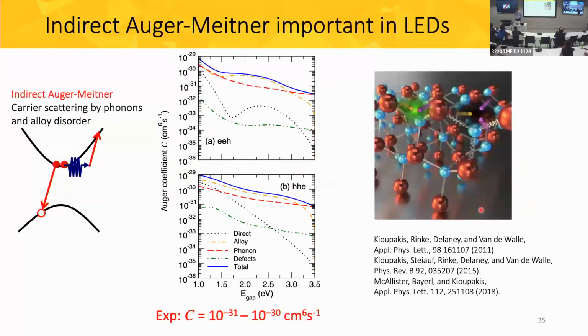A big part of that has to do with the Auger-Meitner effect: the carrier scattering by the phonons and by the alloy disorder gives rise to Auger-Meitner coefficients on the order of 10 to the minus 31, which agree with the range of experimental data, and that explains the potential origin of the efficiency reduction in LEDs. As we see in this cartoon picture, what we want is for an electron and a hole to recombine and give us light, but unfortunately electrons and holes recombine and the energy is taken by another electron or another hole, and the energy is lost to heat.